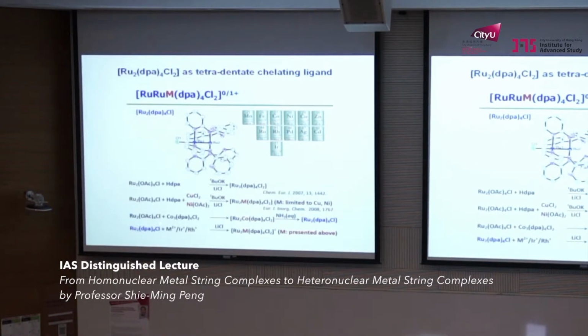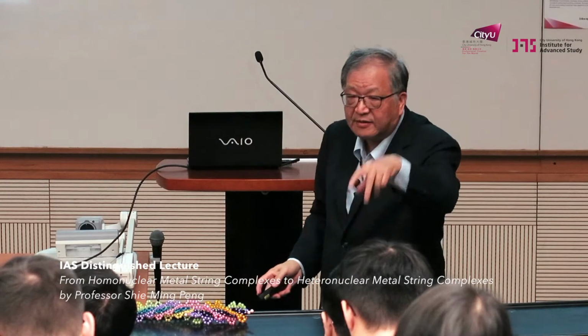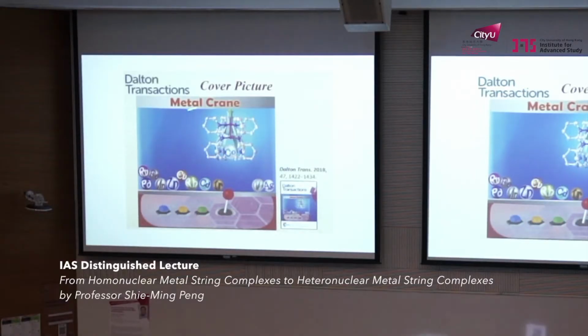For example, when we cook the ruthenium and cobalt, we get the ruthenium-cobalt trinuclear one. Very interesting, in this case, even ammonium can extract out the cobalt ion and become a dinuclear one. And it has four isomers. That means you have four pendant pyridyl groups, so it should be a very good chelating ligand, chelating to coordinate and keep the third ion in this position, from manganese to zinc, from ruthenium to cadmium to osmium. So in this paper, we call it a metal crane. You know, nowadays a lot of shopping malls have those crane machines. Okay, I call it a metal clamp, which can clamp all of the different metal ions.